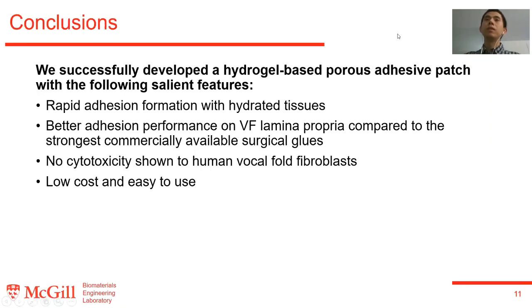So in summary, we have developed a hydrogel-based porous adhesive patch for vocal fold closure. Our adhesive can form rapid adhesion with hydrated vocal fold tissues. The adhesion performance on lamina propria is also stronger compared to the strongest commercial products right now. At the same time, it overcomes the trade-off between adhesion performance and biocompatibility. We hope our progress in this area would bring this next generation tissue adhesive technology from bench to bedside.